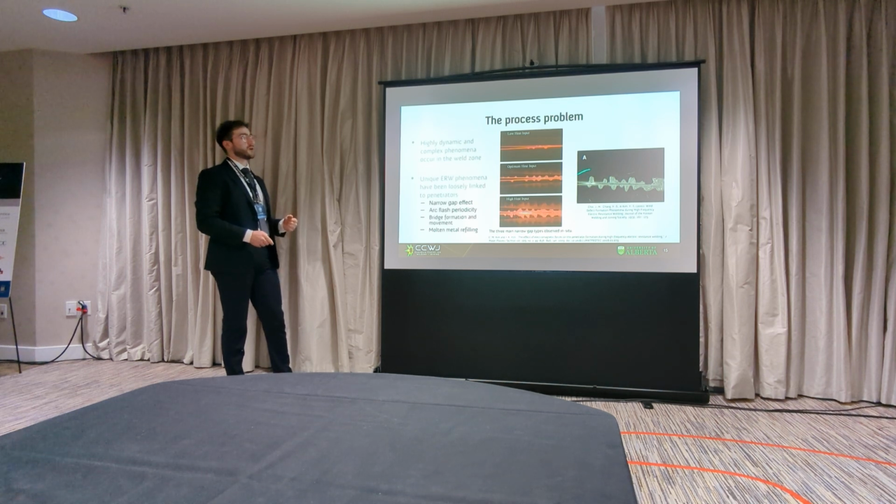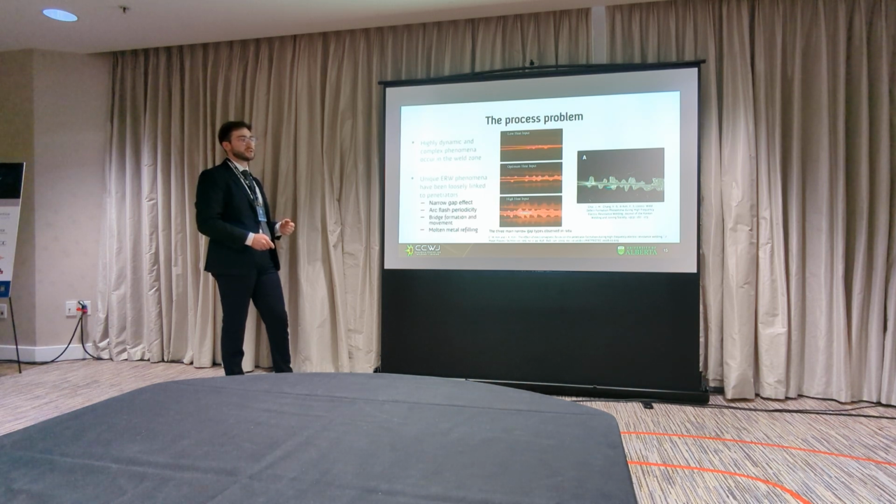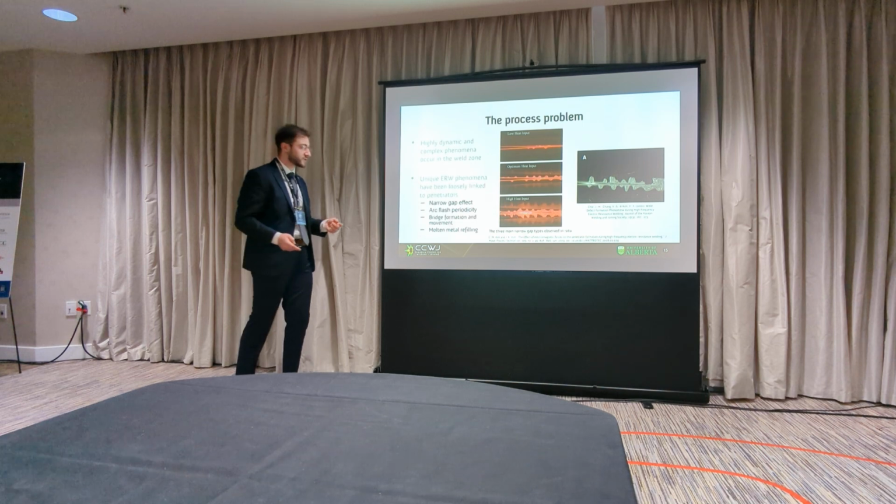There's also been observed arc flashing periodically at a fixed point in the process. And this flashing leads to a molten metal bridge that connects the 2 interfaces, and the movement of that bridge downstream and upstream in the V is thought to be indicative of penetration.